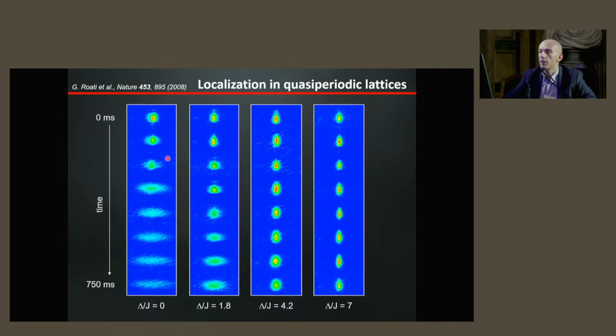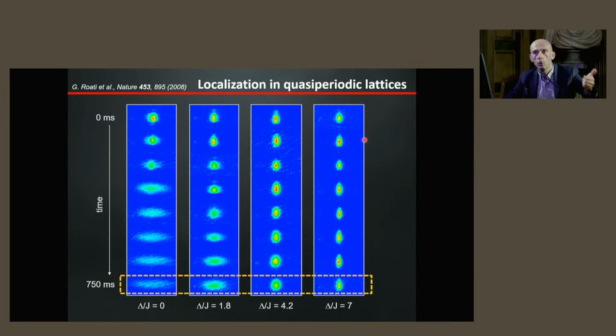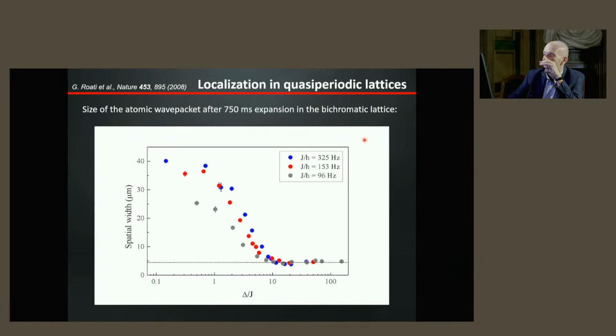...you see that at some point everything gets stuck. And so you have this quantum phase transition from a metallic behavior to an insulating behavior for some critical value of delta. And so this is an observation of Anderson localization, one of the first observations of Anderson localization with matter waves, in this case for a quasi-periodic system, with this quantum phase transition that was predicted for quasi-periodic systems.